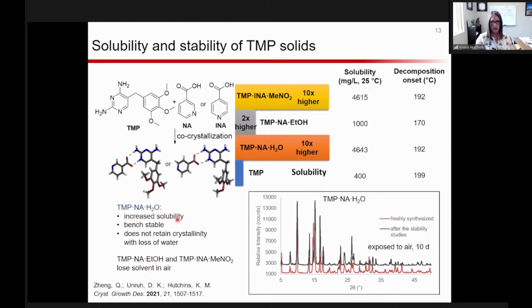And out of curiosity, we were interested in really driving off the water. So we mounted a single crystal on the diffractometer and then heated it up to really force the water to exit. At that point, the crystallinity is lost as the water leaves the structure. It's important to note that the ethanol solvate and the nitromethane solvate actually did lose solvent in air. So when we look at the PXRD data, it does not show as nice correlation when compared to the hydrate system.